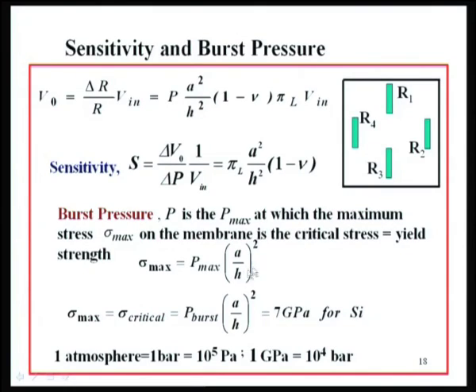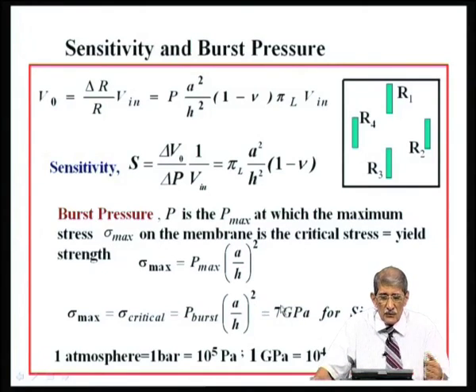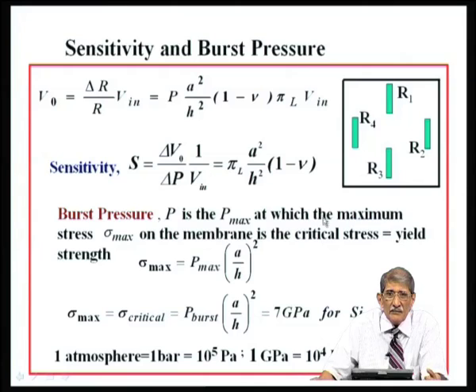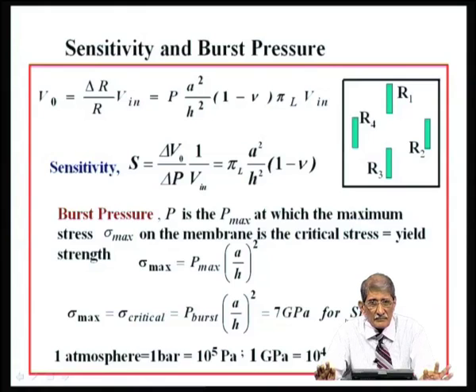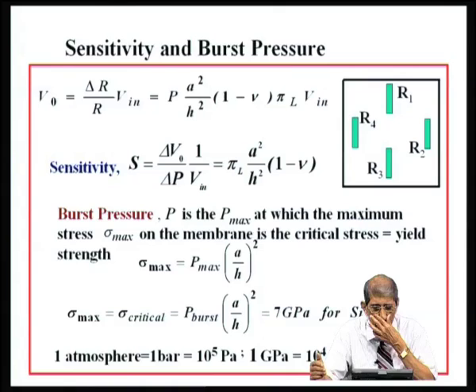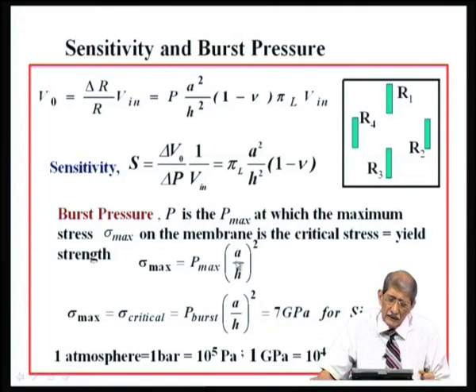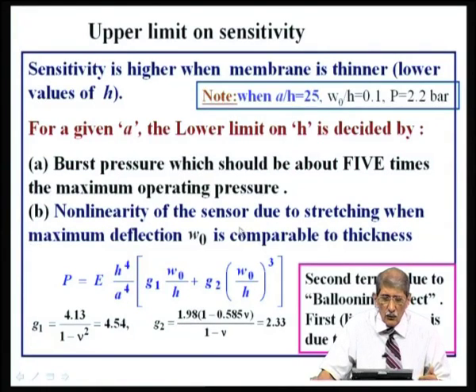So, if H is smaller, this factor will become larger and larger, and for the given pressure, the sigma maximum will be reached at a lower pressure. So, the maximum pressure that you can use will be less if the sensitivity is more. So, the guideline is, thinner the membrane, your sensitivity will be better, but the maximum pressure that you can use will be lower, because it will burst at a lower pressure. Okay. But can you go right up to that maximum stress? That is decided by what is the other upper limit.